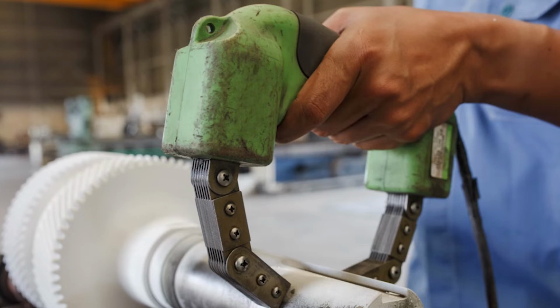We determined through that study that it was about 5 mil of thickness that you could actually still see parts going through a coating. But again, when you are dealing with mag particle and you're dealing with a coated surface, if something is seen, it should always be cleaned and verified. I would never feel comfortable certifying a part if it did have a coating and I saw something. I would want to make sure that that coating is taken off the surface and re-inspected and verified for the